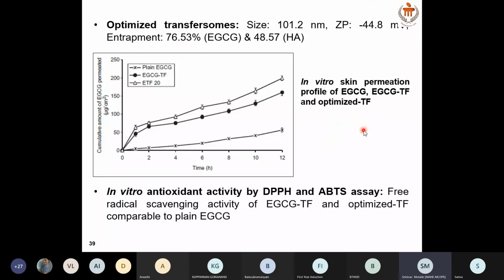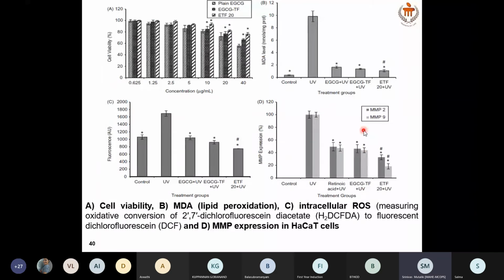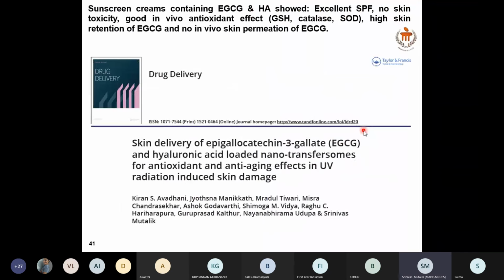And skin permeation study showed that the permeation of EGCG and hyaluronic acid was better in the nanotransferosomal formulation. Then we conducted in vitro antioxidant activity, and it was a big study having the cell viability by MTT assay, then lipid peroxidation, intracellular ROS, and finally MMP, that is matrix metalloproteinase expression in HaCaT cells was observed. So in all these parameters, the transferosome showed better effects. So it got published in one of the good journals.